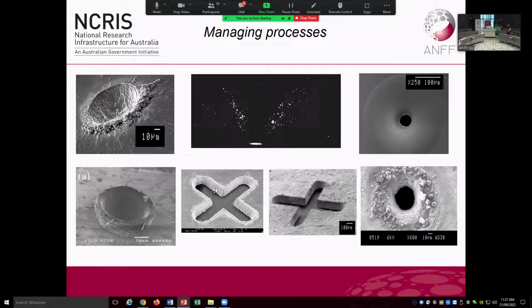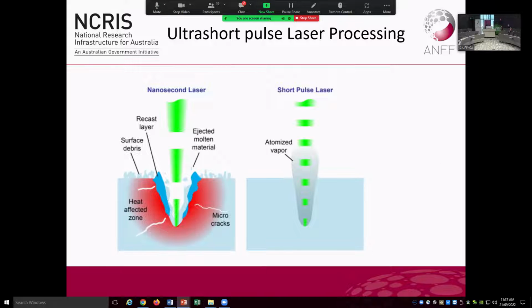What we want to do is be able to take a process which might look nasty like this, where we've generated molten metal, and get it back to something with nice clean edges. And there are a few ways we do that. One is with the CNC routine we use, but also the trend to go towards shorter and shorter laser pulses. And you'll see many diagrams like this floating around the internet when you look up ultra-fast laser processing. And these are mostly from people trying to sell you the laser. So they don't tell the full story, but it's partway there.